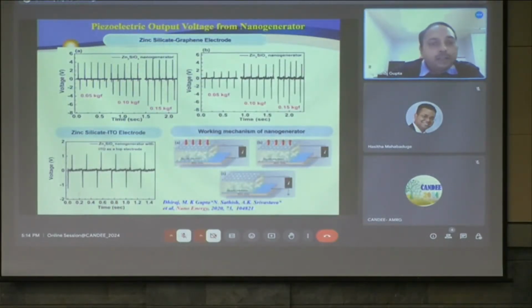Now, the performance of the nanogenerator. We applied very little pressure, 0.05 kg, at 0.15 kg, and we got a voltage of up to 8 volts. In the case of zinc oxide, it was only a few millivolts. So there was many times improvement in the output voltage, and since it was in the polymer matrix, the mechanical durability was very high.